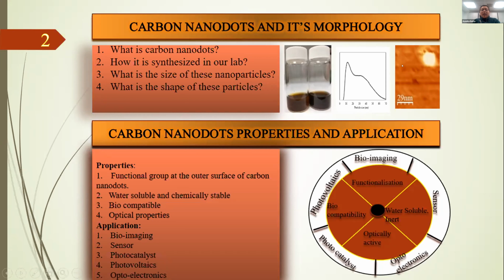But the main reason why such a tiny dot has become so attractive and interesting nowadays is its strong fluorescence. The strong fluorescence is caused by the surface groups. We can tune the optical properties by modifying the surface groups. Because of these surface groups, it becomes water soluble and chemically stable. It is non-toxic and biocompatible in nature. It has different applications in several fields.